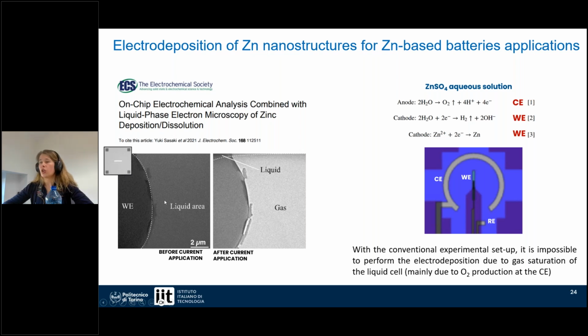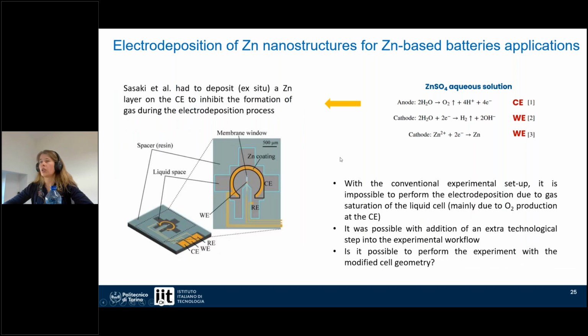And they showed that with the standard configuration, so with the standard small chip, it is not possible to deposit this nanostructure. So basically here I show you the working electrode and the liquid surrounding it. And when the current is applied to perform the electrodeposition, the cell immediately is filled with the gas. So with the conventional experimental setup, it was impossible to perform the electrodeposition due to the gas saturation of the liquid cell, and that was mainly oxygen produced at the counter electrode.